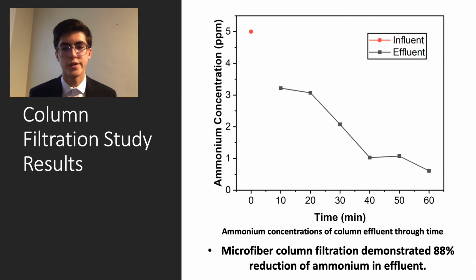Column filtration is a practical method of implementing my adsorbents, and what I found was that using 0.38 grams of microfibers in 200 milliliters of simulated wastewater, there was an 88% reduction of ammonium in the effluent, and the calculated flux of the column was 3 milliliters per minute.